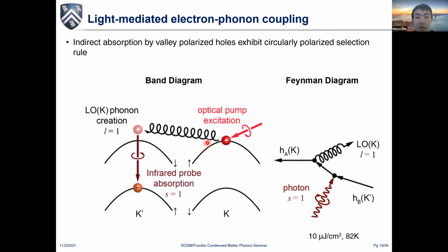The reason we choose 2 energy levels with quite different energy is because then we have to use a photon there, and this photon's polarization tells us if the electron-phonon interaction is chiral or not. So this is a 4-particle process, and then we can identify the phonon's angular momentum by the incident photon's angular momentum.